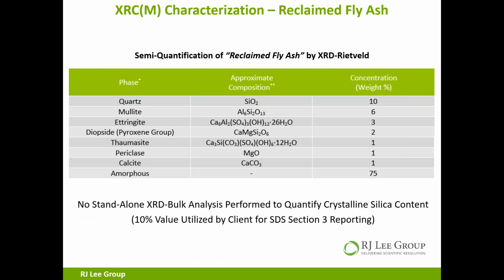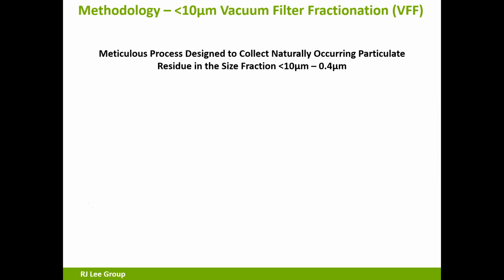Okay. Reclaimed fly ash, the last product. Again, with the Rietveld, we see that we now have 10% quartz. So these numbers are all pretty close to each other. Okay. The calcite's at 1%. No standalone XRD bulk analysis. We don't need it. We already know that we've exceeded the GHS. There's no reason to run a separate bulk. So this 10% would be the value that would be utilized for Section 3 reporting.